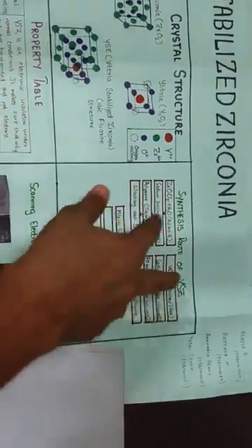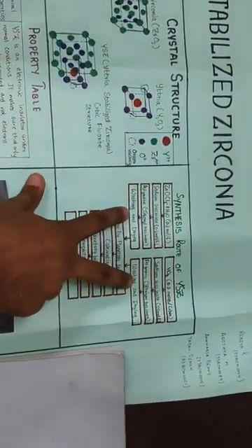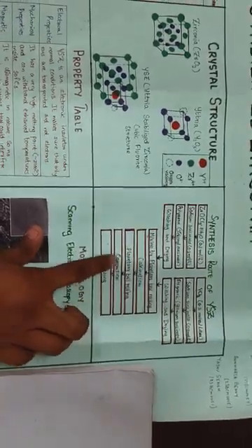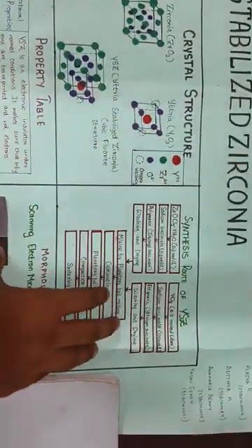Similarly, for YCl3 also we react it with sodium succinate, through which we get yttrium succinate, and we wash and dry this. After getting these two compounds, we mix them by planetary ball milling, then we calcine it, then after planetary ball milling and compaction, we sinter it. So this was the synthesis route of YSZ.